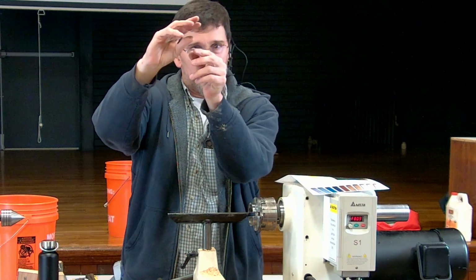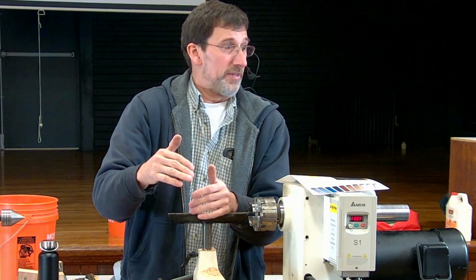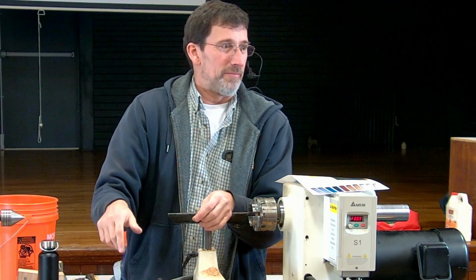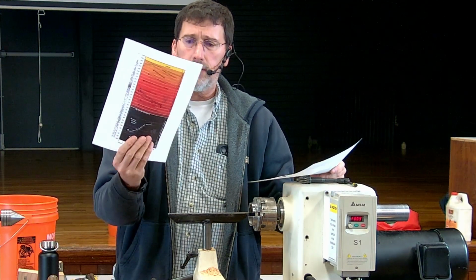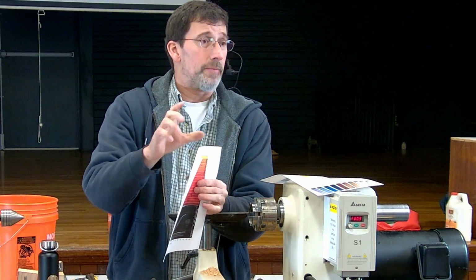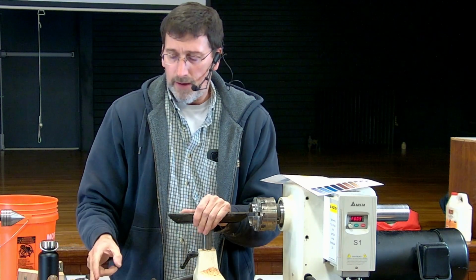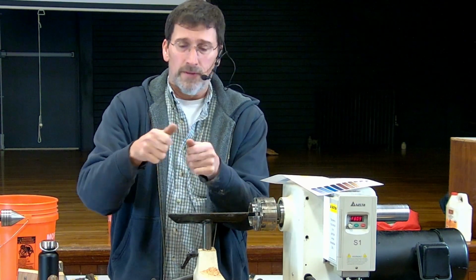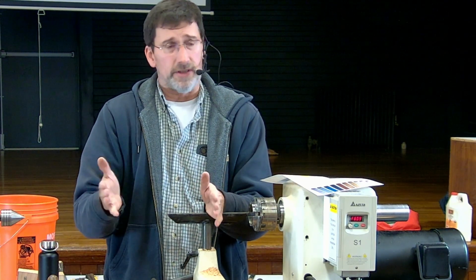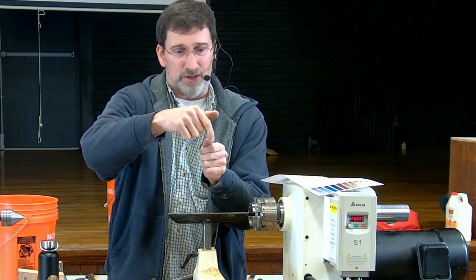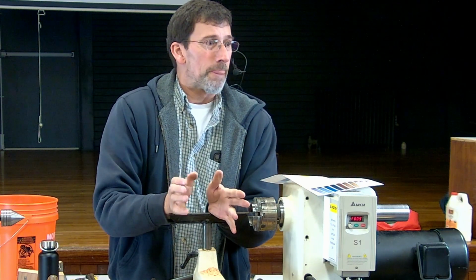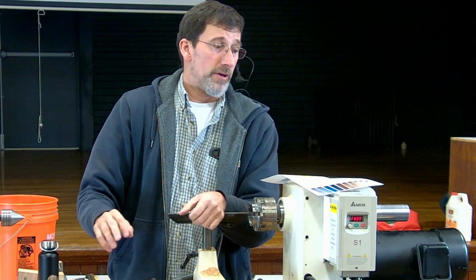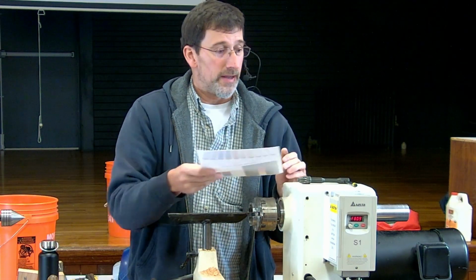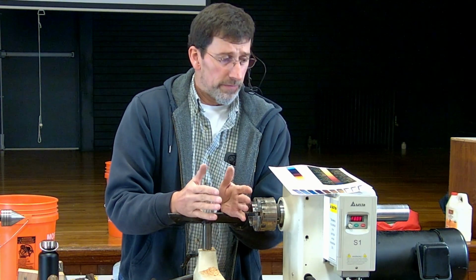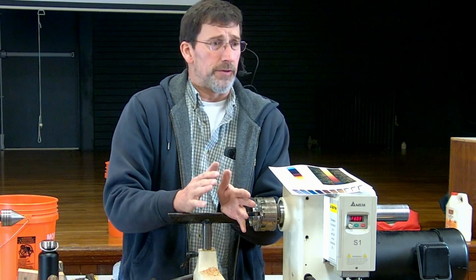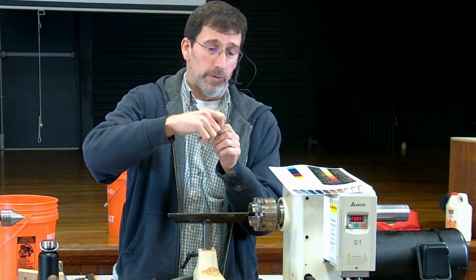If you pull it out and the metal breaks in half by itself, you got it too hot. But it's a lot of work to get metal to that point. The 1500 degrees, quenching it in oil, that makes the metal hard. I've taken tools straight from the hardening, ground them, used them, and then I decided to put a burr on one, and the whole edge chipped off. It was too brittle. So to make it a little bit softer without losing the hardness, you need to temper it. And tempering, you would heat it up anywhere from 400 to 500 degrees. And that makes it soft enough so it won't chip.